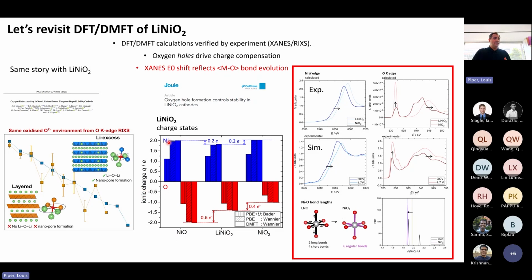And what we found is there are variations with which level. So if you go at NiO, use different levels of code, different levels of sophistication in the model, you do see variances, but essentially all of them agree that as you go from lithium nickel oxide to NiO2, there is a tendency that more of your change of electron density, where your electrons are being abstracted from, spatially comes from regions which are closer to the nickel ion than to the oxygen ion.